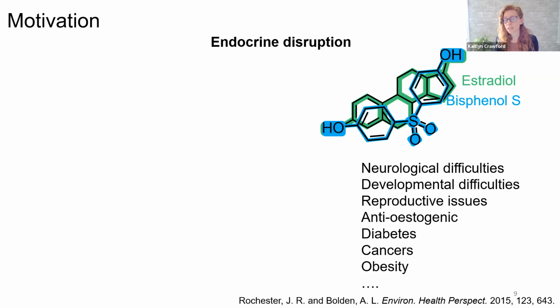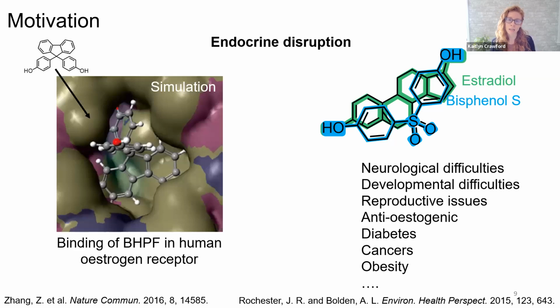The problem is that even though our commercial devices now are BPA free, it doesn't mean they're not BP something else free, and that those materials may also be causing endocrine disruption. And in fact, there's multiple literature articles that report and show that these actually do have endocrine disruption. So here's a Nature Communications paper from a different group that I've referenced to motivate this work that shows a simulation that the BHPF fits inside the estrogen receptor and causes endocrine disruption. And there are multiple papers as well showing that BPS is also an endocrine disruptor. This is a big issue for us because these molecules have not been banned or regulated, at least here yet.